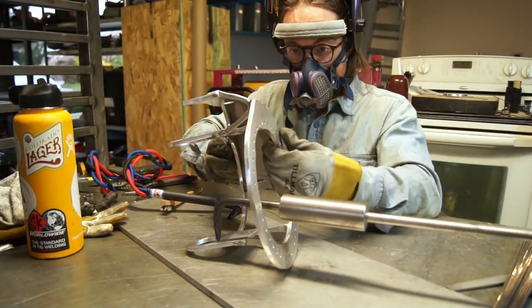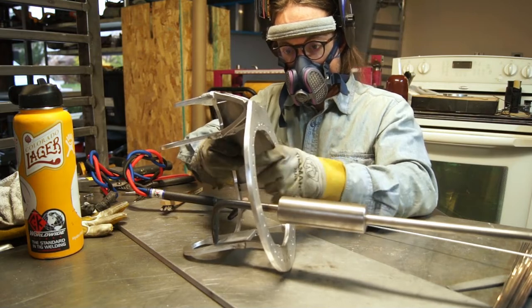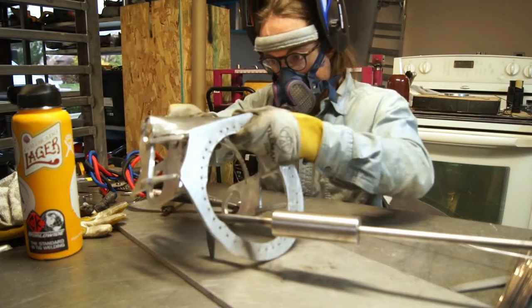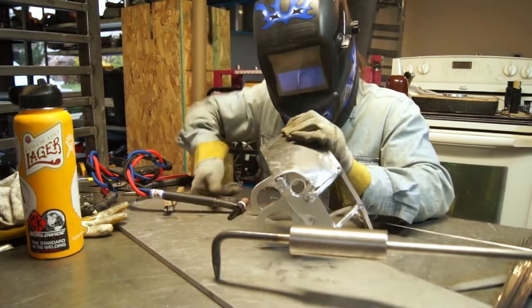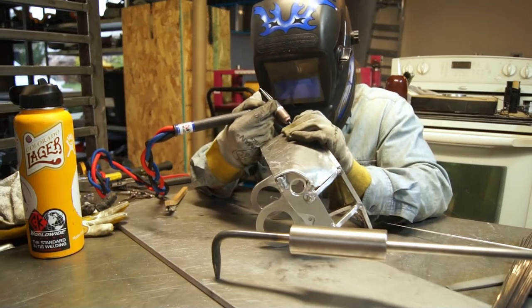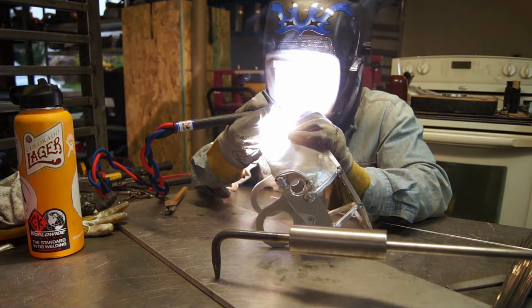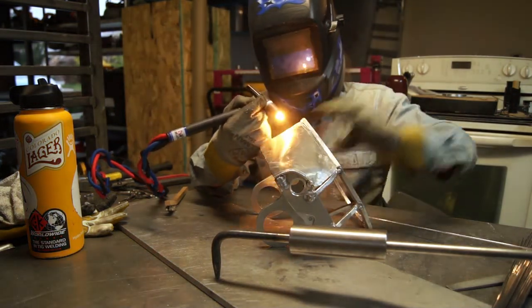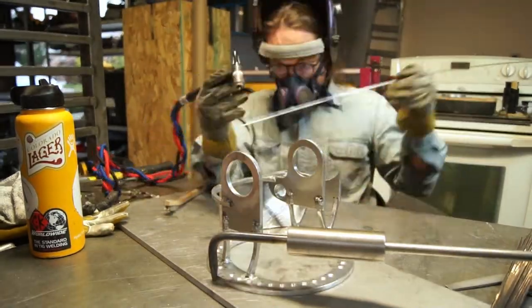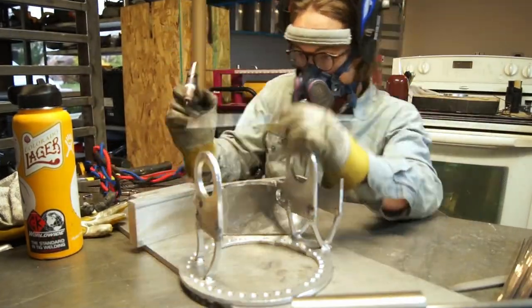Ran a tack there. I usually run my tacks with some filler wire because they like to move. That part moved, by the way - I don't know if you caught that, but that part shifted on me. That was fine, I was able to push it back into place because I had a large moment arm on it. Doing another tack - I almost burned my hand. I find my tacks crack if I don't use filler wire.